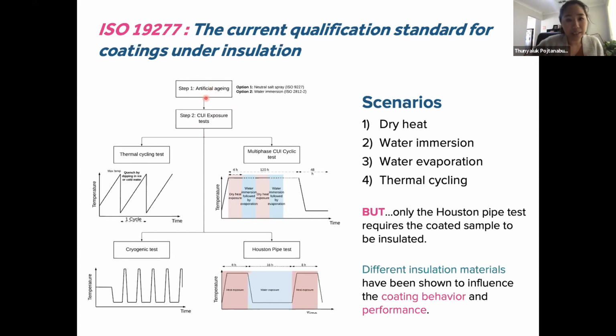First, they suggest that the coating should be artificially aged to simulate different conditions, such as when the coating is applied as a module, and then it takes a while before the component gets insulated. So that coating could be exposed to UV or salt spray for a period of time. That is step one, which is artificial aging.